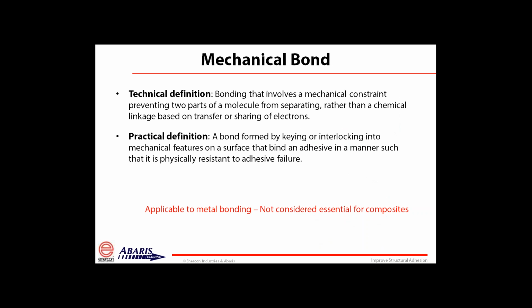Well, in the past, the idea of getting a mechanical bond, because we've always done that with metals, and also a chemical bond, but mechanical bonding being a valid way of getting a good bond on a composite has pretty much proven to be wrong. The definition of a mechanical bond basically is where you're creating some kind of surface topography or very rough surface in which you can get more surface area at a very large scale, at a macro scale, and do that in a way that you will lock in the adhesive, interlocking into mechanical features on that surface.